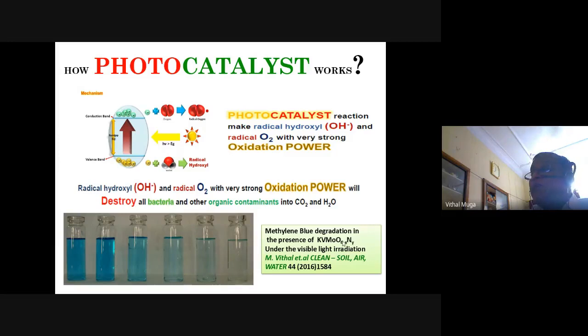But what we have done is we have doped this oxide with nitrogen. Nitrogen doping will alter the band gap energy of the photocatalyst, and now it can absorb visible light and then eventually attack the methylene blue, and it will decompose. Now you can see this, on the extreme left, this is 0 time irradiation. On the extreme right, 180 minutes irradiation of visible light. You can see that it has almost disappeared. One of my students, Mr. Raji Reddy, has done this work and published it in a journal called Clean Soil Air Water. This is a widely read international publication from 2016. A wonderful piece of work.